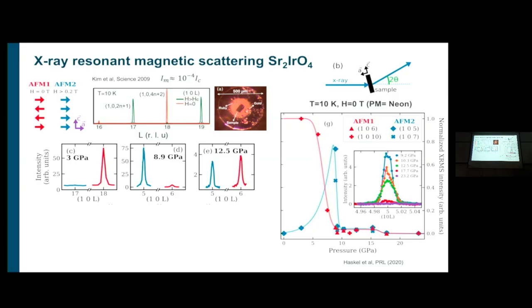But then as I go up in pressure, it switches. All of a sudden, I see the odd peak and not the even peak. And if I go to higher pressures, they become equal. So this is what happens. It's a crossover from this type of magnetic stacking of these ferromagnetic moments along the z-axis. It goes from here to here without applying a magnetic field, just by squeezing the thing. That's quite interesting. That's because you're changing the exchange interactions between these layers.